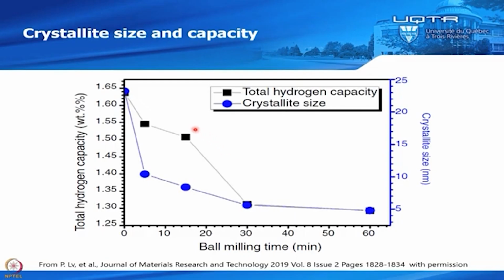So here we plot this, the hydrogen capacity as measured as a function of milling time, and you see that the capacity is going down. And here this is the crystallite size, again as a function of milling time, and you see the crystallite size is also decreasing and it looks similar. So probably these two are related. So this is what we will see in the next slide.